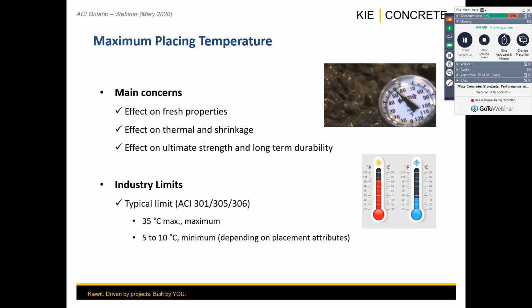The main concerns for placing temperature typically come from the potential detrimental effects to fresh properties. Let's say that you have air-entrained mixes, and you're going to have to pump the mix, and you're going to create friction, and you're likely going to have slump losses and air losses. That's part of the discussion when you're talking about maximum placing temperatures. Thermal effects and shrinkage are also likely going to be affected depending on the placing temperature.